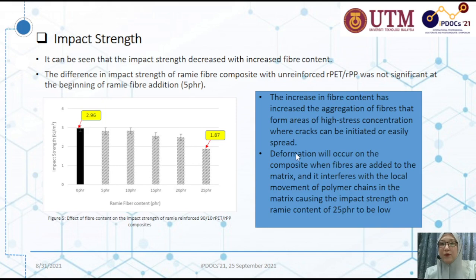The increase in fiber content has increased the aggregation of fibers that form areas of high stress concentration where cracks can be initiated or easily spread. Deformation will occur on the composite when fibers are added to the matrix and it interferes with the local movement of polymer chains in the matrix, causing the impact strength at the ramie content of 25 phr to be low.